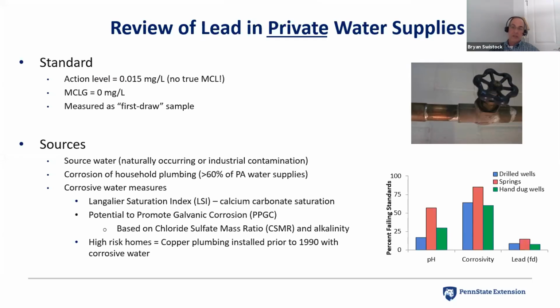When it comes to corrosive water, it is extremely complex. There are different indices that we use. None of them are perfect, but there is what's called the Langelier Saturation Index, or the LSI index that we use. It's a calcium carbonate saturation index, which basically looks at the nature of the water and whether it's going to deposit calcium carbonate or whether it's going to leach materials from the plumbing. And so negative LSI values indicate corrosion, and positive LSI numbers mean scale formation, where scale will be deposited in the pipes. There's also a galvanic corrosion index that we can use. The potential to promote galvanic corrosion, which is based on the chloride to sulfate mass ratio. This ratio became more popular and became more aware from it because of what happened in Flint, Michigan, because increased chloride levels can cause more galvanic corrosion to occur.